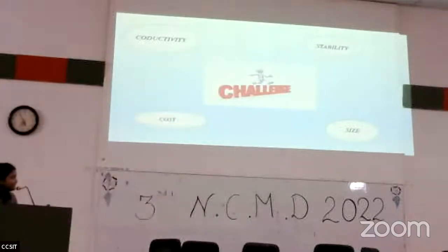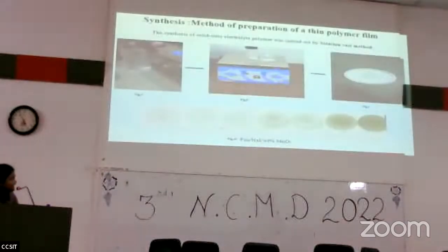Before doing the experiment, I considered different challenges, and some of them are conductivity, stability, cost, and size. I did the synthesis with the help of the solution cast method. First I put PEO, NaI, and acetonitrile. Then I put it on a magnetic stirrer, and after 7 or 8 hours, it is cast and it looked like this. As you see here, the color changes by increasing the weight % of MnO2. First my film is white, and after that the color deepens.